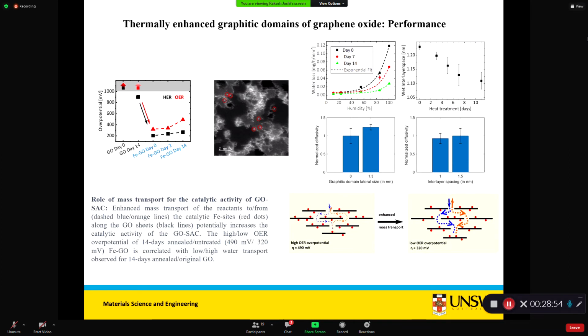And then what we did, we have a very good catalyst group at UNSW. They said that if you could reduce graphene oxide, let's use it for catalyst. So we collaborated with Professor Rose Amal's group, and then we see that when I say day 0 it means the pure graphene oxide, and 14 day means the most reduced graphene oxide. Here we see the HER is improved. So this is the worst HER OER performance. This is the best HER OER performance.